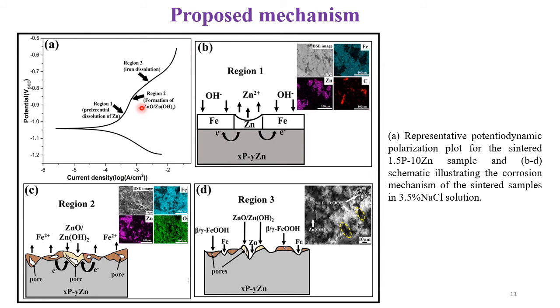And coming to the proposed mechanism, as you can see here from the potentiodynamic polarization plot, the anodic dissolution behavior comprises three different stages. One is the dissolution of zinc due to its highly active nature, and then there is passive film formation of ZnO and Zn(OH)2, as a result of which the adjacent iron matrix now acts as the active site and undergoes further dissolution. So there is an alternate dissolution of zinc and iron in the hybrid anodes, as a result of which it continuously dissolves, and the final morphology is basically uniform in nature, which is one of the most important criteria for a promising sacrificial anode.